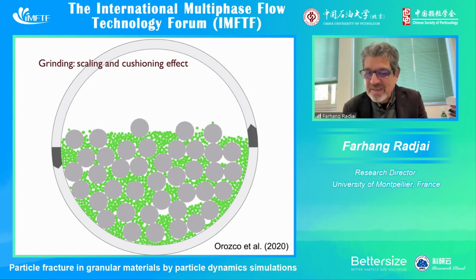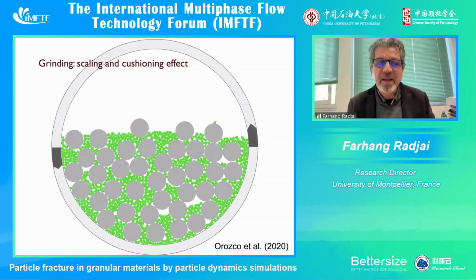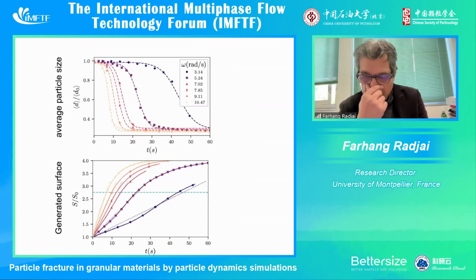So we can't have many particles, but still, even with a limited number of particles, by analyzing the data and evaluating the fluctuations, we can have very smooth data. Here you see, for example, the evolution of the average particle size, normalized here with the initial particle size for different rotation speeds. As you can see, they are very well defined. Or the surface generated, so the specific surface generated during grinding. So we studied, for example, the initial rate of surface generation.